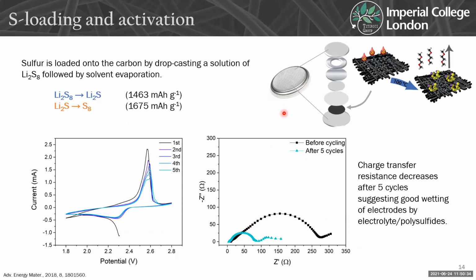So then I assembled these carbon fiber mats into some batteries. And typically with lithium sulfur batteries, people start with elemental sulfur, but with these fibers, it's actually a lot easier to start not with sulfur as starting material, but already with the lithium polysulfide. So here I started with Li2S8. The advantage of that is you can drop cast it onto the mat, and if you know the concentration, you know the volume, then it's very easy to control your sulfur loading. So then we do a first discharge, and that has a theoretical capacity of 1460 milliamp hours per gram roughly, and then you charge it fully and you go back to sulfur. So in theory you should obtain the full capacity from that.